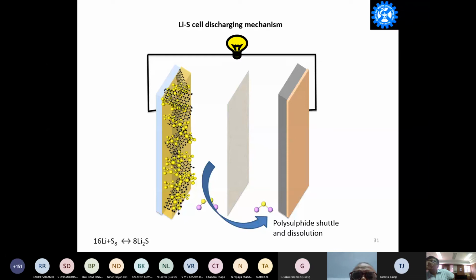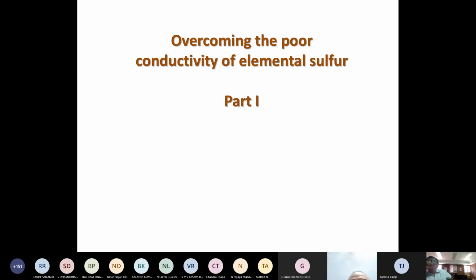So in the case of a lithium ion battery, only the lithium ion is migrating from the anode to cathode. But in the case of lithium sulfur, not only lithium ion is migrating. In addition to that, sulfur species are also moving because of the formation of the polysulfide. This is inevitable. So, as I said in the beginning, there are four major issues. One is the poor electronic conductivity of sulfur, the second one is the undesirable shuttling of the polysulfides along with the lithium ion, the third one is poor interfacial property, and the fourth one is self-discharge.